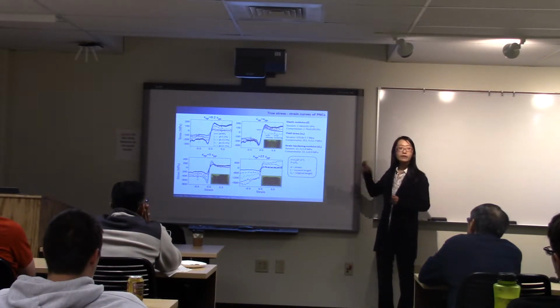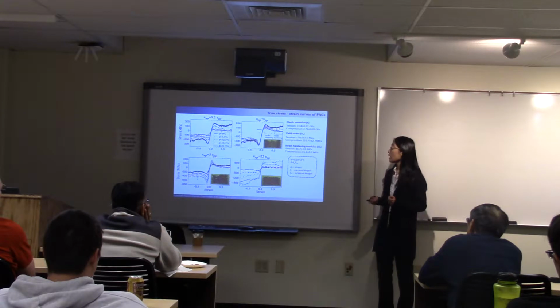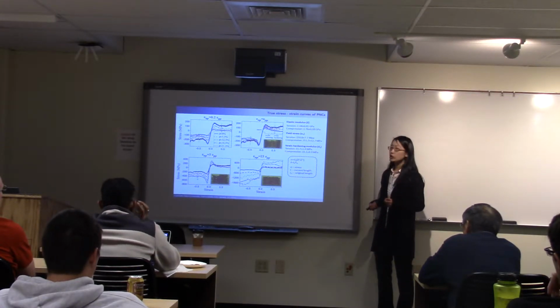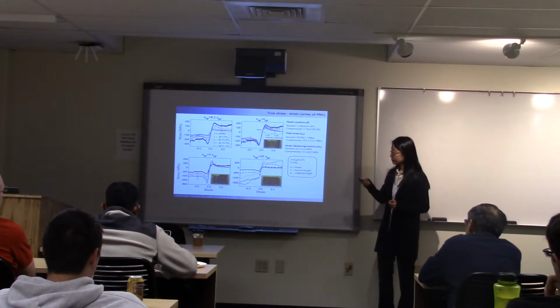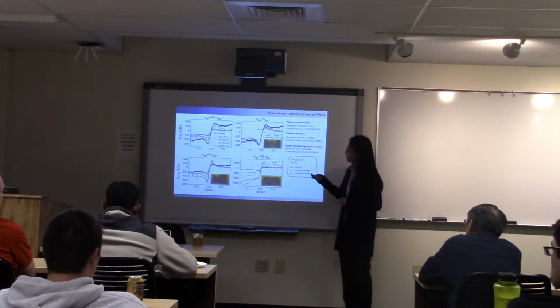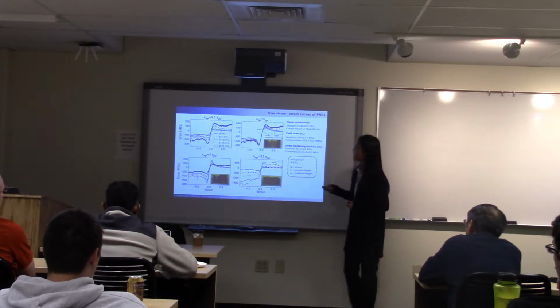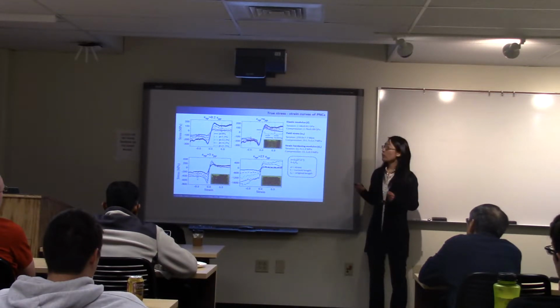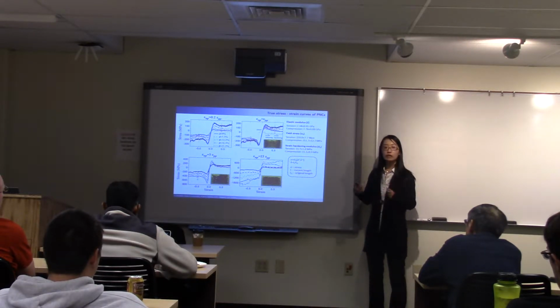And we have compared these results with the available experimental data as well as previous simulation results, and they show pretty good agreement. And the four different plots represent the different nanoparticle-polymer interaction strengths from very low to very high. And the different curves represent different nanoparticle loading volume fractions.